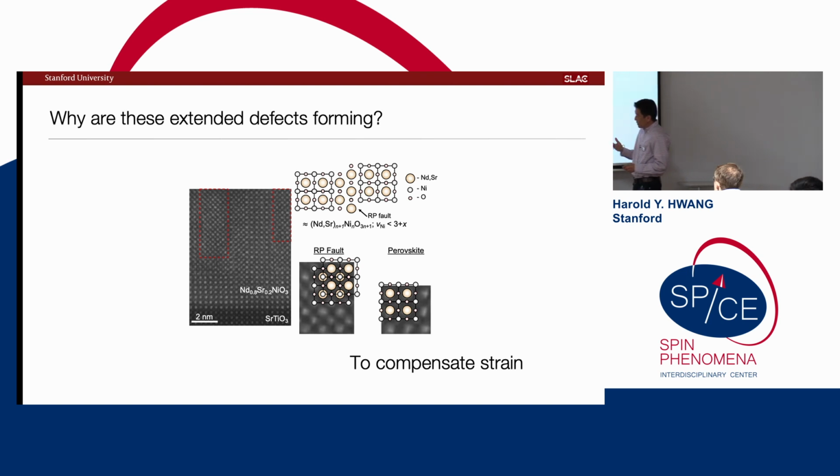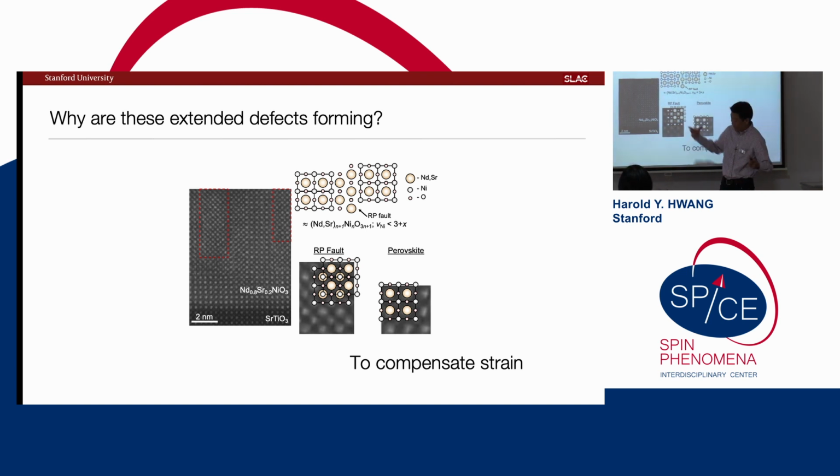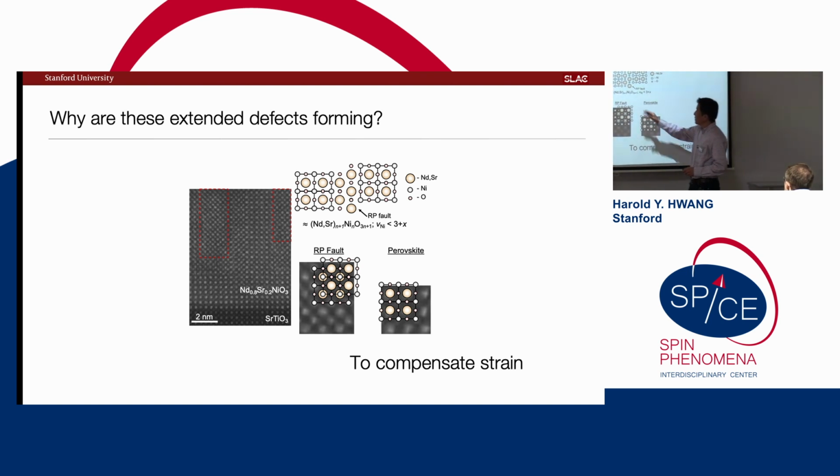And so at least our initial efforts were to grow this perovskite form heavily strained, right? We're basically trying to grow this on a lattice that wants to pull this apart by 2.5%, 3%. And a natural materials instability then is these sorts of extended defects. What I want to communicate is it's a way for the lattice to stretch itself out. Right?